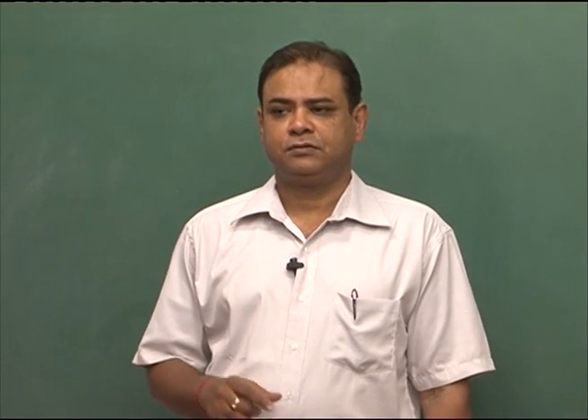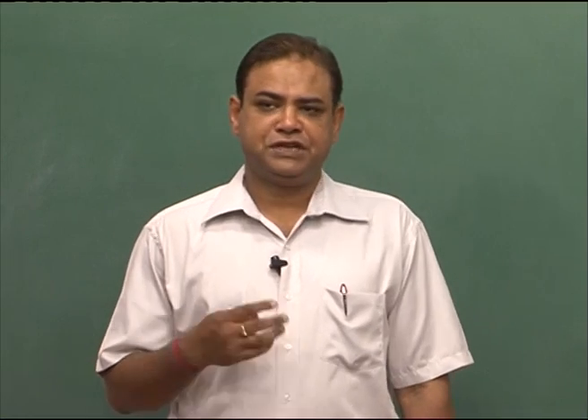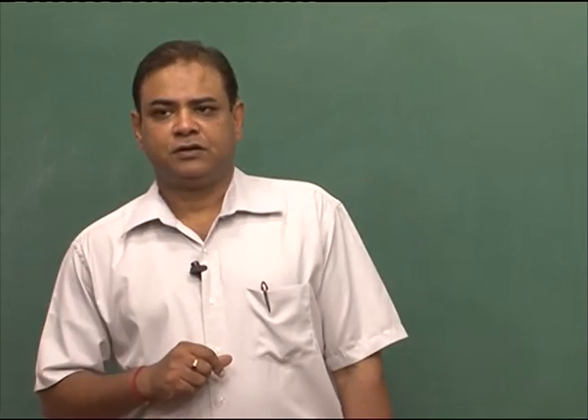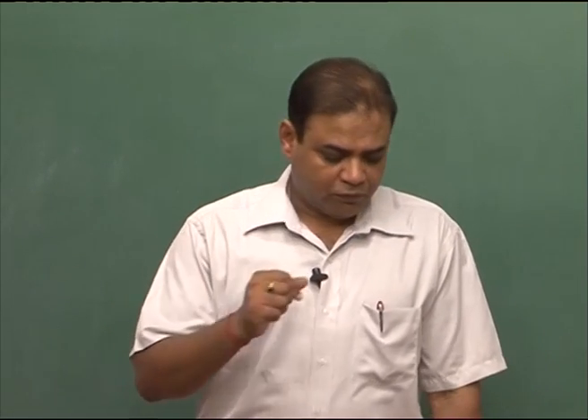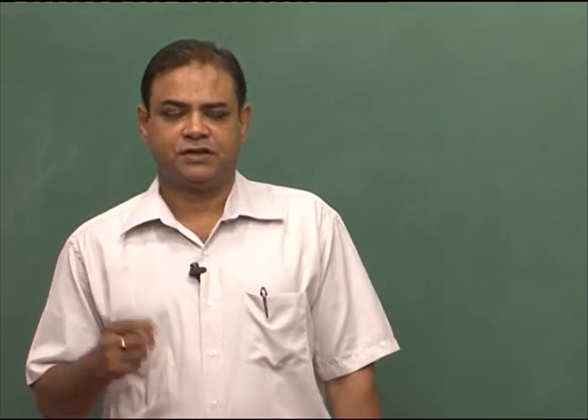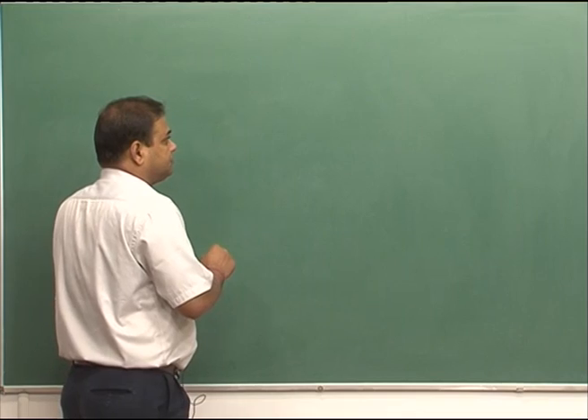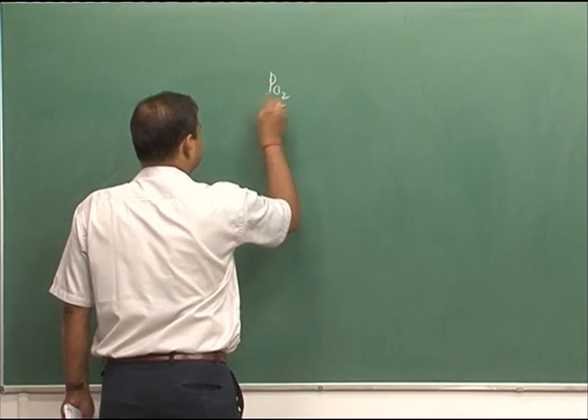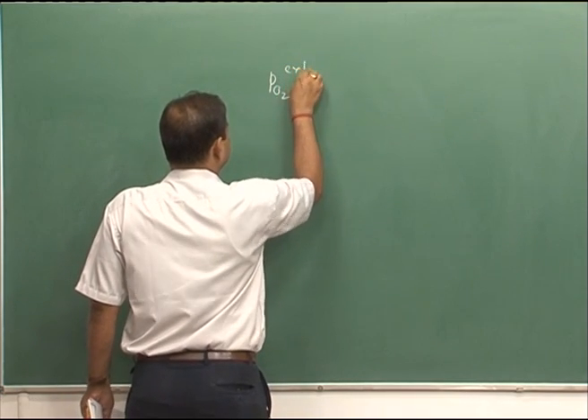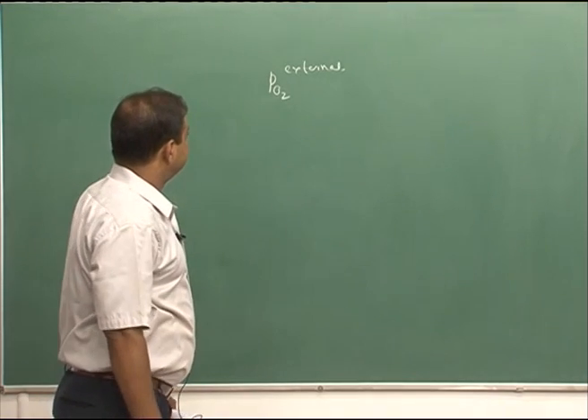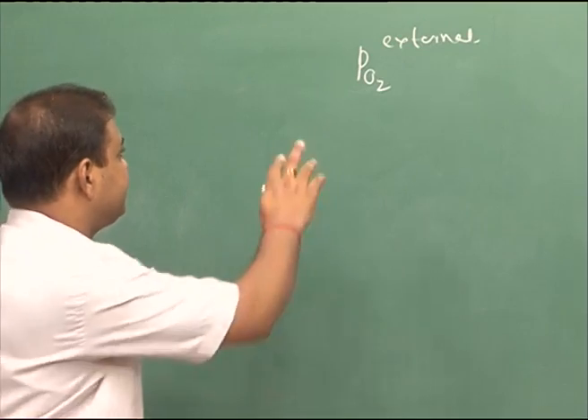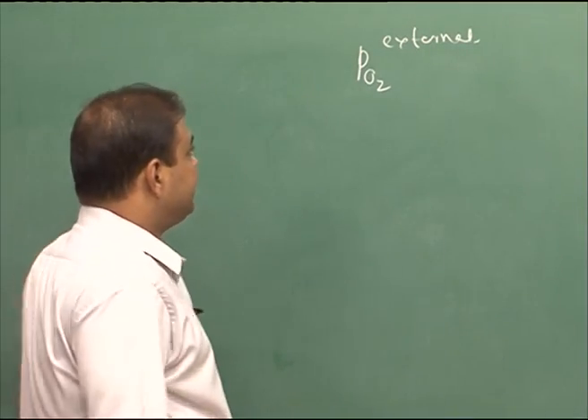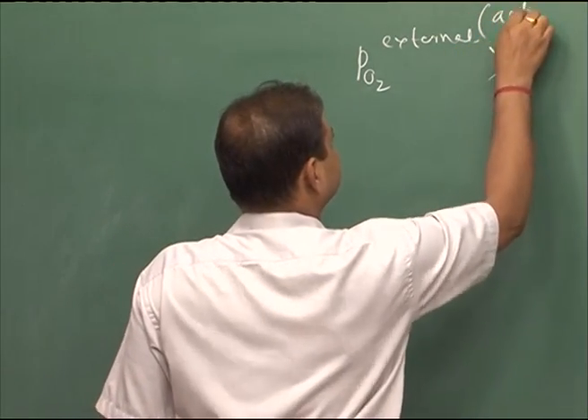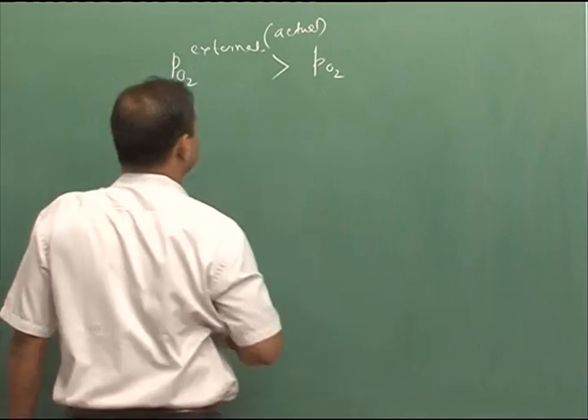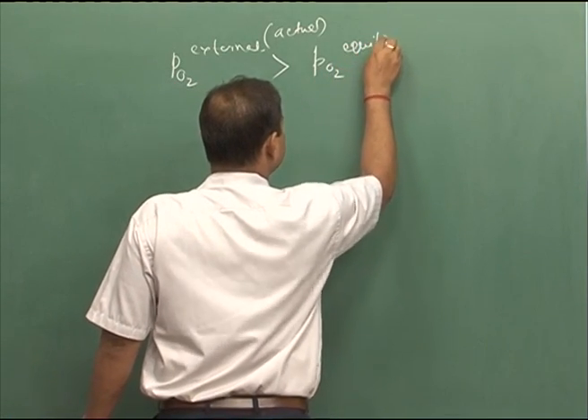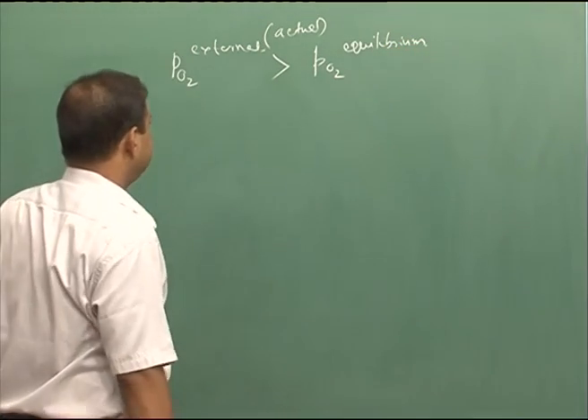We have seen that the partial pressure of oxygen needed for the formation of oxide is decided from the free energy change for the process of oxidation. And also we have seen that if the external partial pressure of oxygen in contact with the metal is greater than the partial pressure of oxygen at equilibrium, then oxidation would be favored.